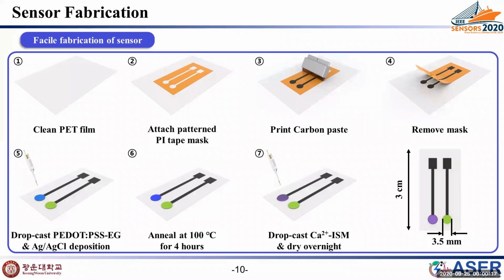Now I will explain how to fabricate the sensor. First, prepare a clean PET film and then attach a patterned PI tape mask. And then carbon paste was printed and the PI tape mask was removed. The prepared treated PEDOT:PSS was dropped on the ISE and dried at 100 degrees C for 4 hours. Finally, the prepared calcium ion-selective membrane was dropped onto the working electrode and dried overnight.